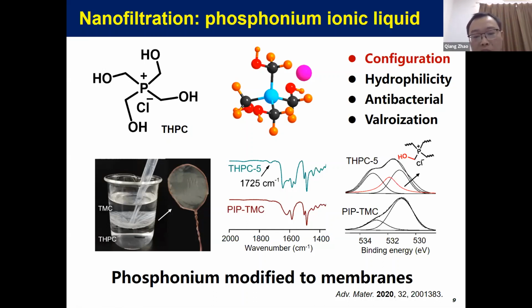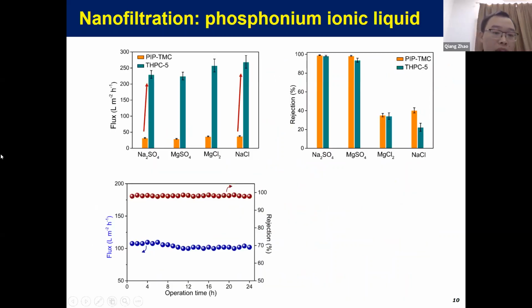And then by using FTIR and XPS, we can really verify that the membrane undergoes an esterification reaction with the aqueous and organic phase monomer to form the thin film. These membranes were then tested by cross-flow nanofiltration.